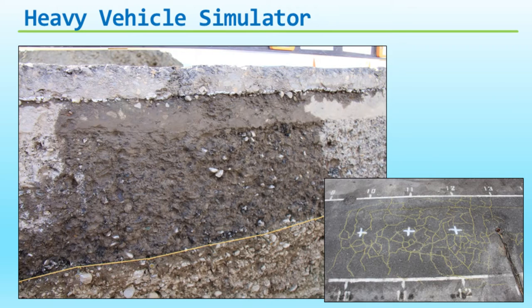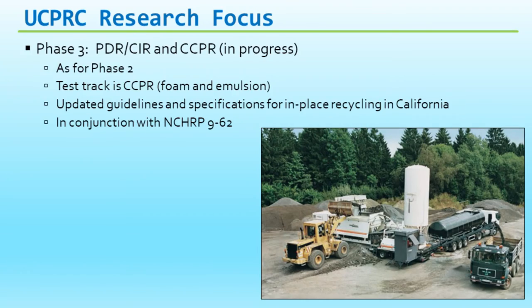But again, this had something like 18 million ESALs on it. It was wet. But there was absolutely no distress, no rutting or anything in that underlying layer. The layer was still in perfectly good condition. So yeah, you could rip that surface off, put a new surfacing on it with a decent tack coat, and you'd be just fine. And then finally, this is phase three.